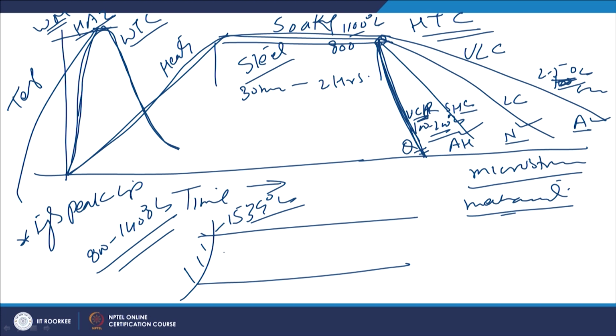Then in the regions away from the fusion boundary, the temperature will be decreasing, like say 700 degree centigrade, 900, 1100, 1300, 1500. So, on approaching towards the fusion boundary, the peak temperature will be high. At the same time, another point which we have to see is the time above which high temperature is maintained. So, this high temperature retention period is very short.